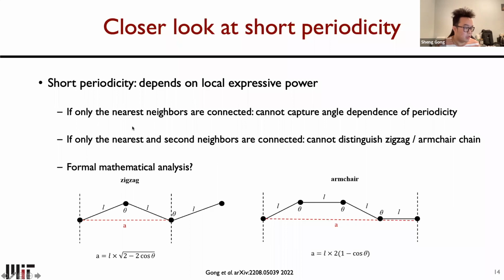To illustrate the effect of local expressive power on capturing this periodicity, we can think about some toy graph neural networks. For example, if a graph neural network only connects the nearest neighbors and does not consider the bond angle explicitly, then we can imagine that this most simple graph neural network cannot capture the angle dependence of periodicity. Therefore, although this periodicity is very short, the graph neural network cannot correctly capture the periodicity of these zigzag chains or armchair chains with different angles.